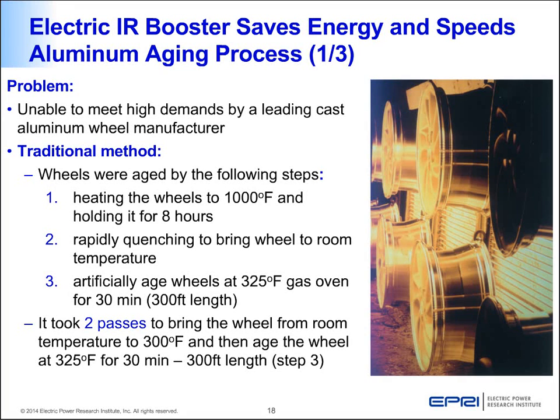So the traditional method used by the customer involves three steps. The first step is heating the wheels to 1000 degrees Fahrenheit and holding it for 8 hours. The second step is to rapidly cool by quenching the wheel to room temperature. And the third step is artificially aging the wheels in a 325 degree gas oven for 30 minutes. All these three steps have to be completed in order for the wheel to come out of the production facility.